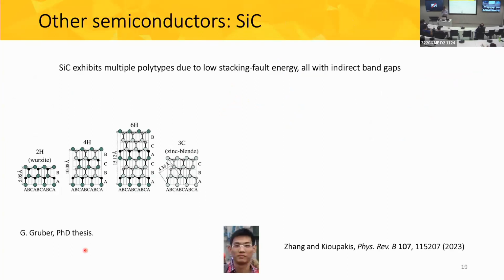All right, so we can take this method and we can apply it also to other semiconductors with indirect band gaps. And the famous case is silicon carbide. Now, silicon carbide has many polytypes. And the reason for that is that the energy it takes to cause a stacking fault is very low. So there are many, many polytypes that involve different stacking sequences of the silicon and carbon atoms.